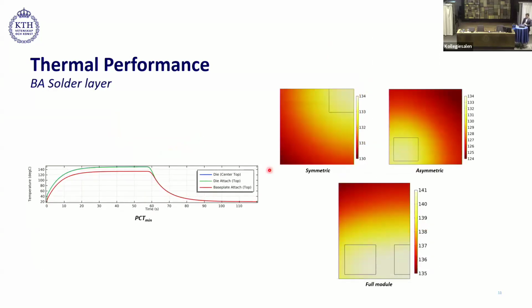Now looking at the thermal performance of base plate attached solder layer, this is analyzed during PCT-min. And we see that depending on the location of the die inside the package, the temperature distribution inside the base plate attached layer also changes. For example, in symmetric, we have the high temperature region in the center. However, in asymmetric case, the high temperature region moves towards the corner or the edge. Additionally, the presence of more die introduces more high temperature region, I will say.